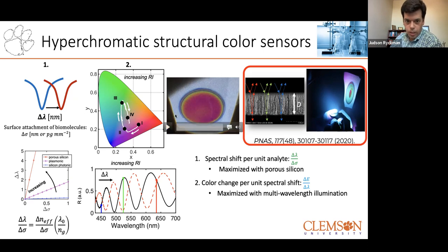So here's a sample here that you can see starts off as kind of this magenta red, fractions of it are a little bit yellow on the edge. But this is a porous silicon thin film interferometer. It's about 1 micron thick, and it has pore diameters around 30 nanometers. So let's take a look at what happens in response to water vapor. So you see pretty immediately as the vapor begins to condense inside the pores, there's a strong color change. And this trajectory in white here is actually measured from this video, which is taken with an iPhone camera.